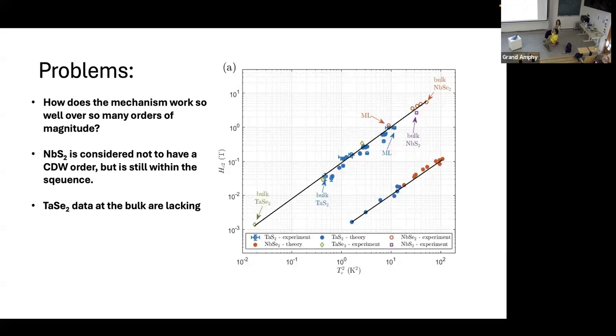But there are several problems with this theory. One is that people claim quite forcefully that niobium sulfide has no charge density wave. So why would it be here to be further up? People don't measure the charge density wave, but this curve behaves as if there were one.